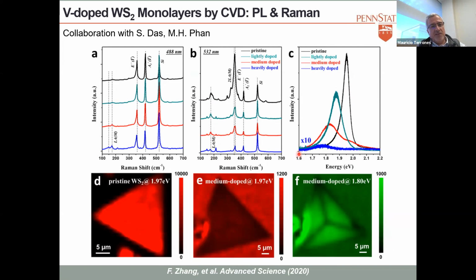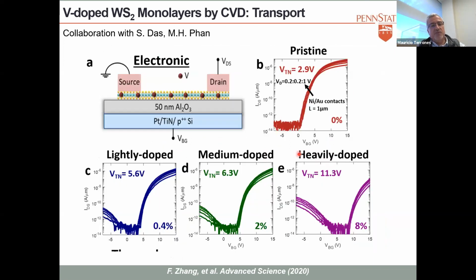And the nice thing about this system is that when you measure transport, you start to see changes in the electrical transport. So it's an N-type semiconductor, and as you can see, this is the N branch of the semiconductor, and these are different devices that were made. So as we start introducing vanadium, we can see that the P branch starts developing. So you start to have a P branch and bipolar behavior, which is very interesting. And then when you have it heavily doped, you have this nice bipolar behavior.